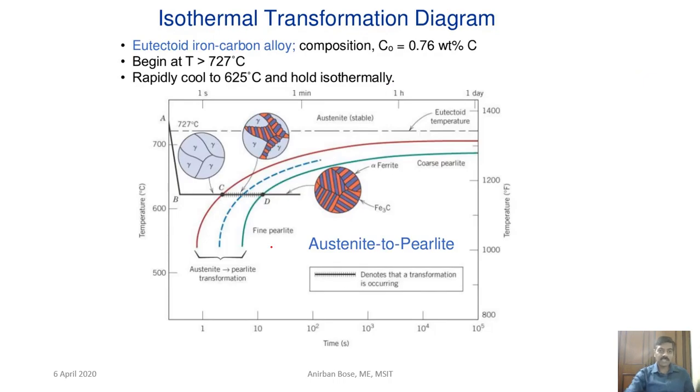So you can see this isothermal transformation of austenite. Suppose this is the cooling curve, A, B, C, D is the cooling curve. Initially, suppose you have heated it into the austenitic range, and then gradually you are cooling it. Suppose initially you are cooling it very fast up to point B, then you keep it at a constant temperature, maybe in a salt bath, inserting it for a long time.